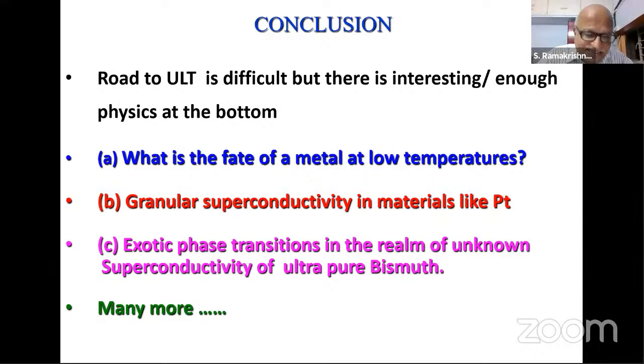In the case of a normal BCS superconductor, the pairing was established because people found that it is oppositely paired, that the charge of the Cooper pair is 2e, and so on. These came from experiments. Unfortunately, it is easy to do experiments at one Kelvin or above, but very, very difficult at microkelvin. So we need to do more to understand what the glue is. But this is the thing: because of its high dielectric constant, the holes can bind together and overcome the Coulomb repulsion.